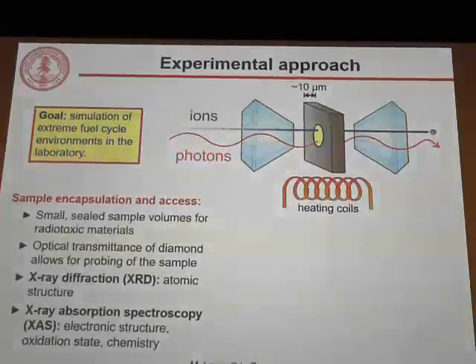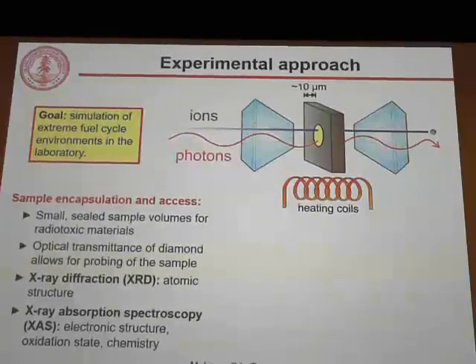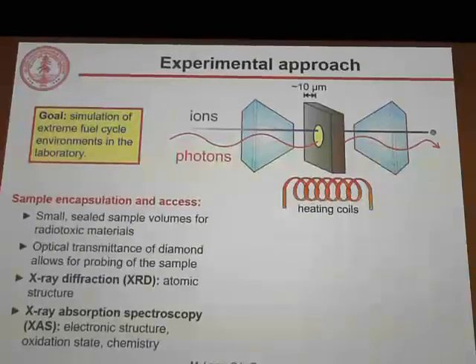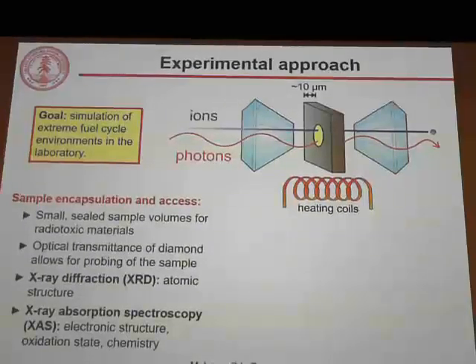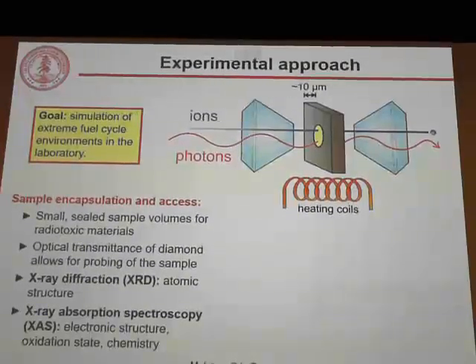Now, my experimental approach is based on simulating the extreme fuel cycle conditions of interest, which often involve these extreme conditions in tandem. So I use a sample encapsulation environment based around a diamond anvil cell. So we squeeze the sample here between 2 of these diamonds, which we can use to apply pressure, or if we're not interested in pressure, it's still useful because it seals the sample, which is nice when we're working with radiotoxic materials, especially when we're using them at user facilities like synchrotrons for characterization. We can heat the samples using heating coils through resistive heating. And what's nice about diamonds is that they're low density, so we can pass ions through them into our sample to simulate irradiation in a reactor or from alpha particle decay and so on.